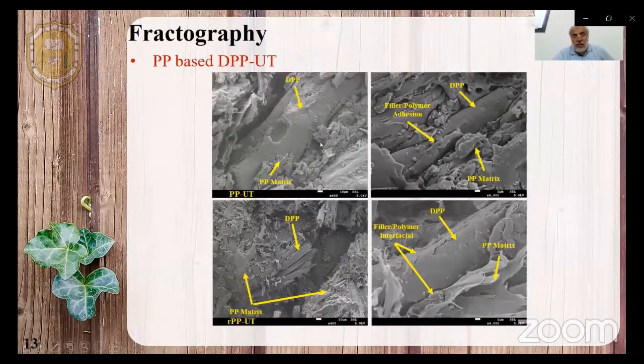To support this, SEM images for the tensile strength: for the untreated cases, we can see here there is some weak interface between the DPP, the date palm powder, and the matrix. This picture is just a magnification of this one. So for both virgin PP and recycled PP, we can see here some issues for the interface.